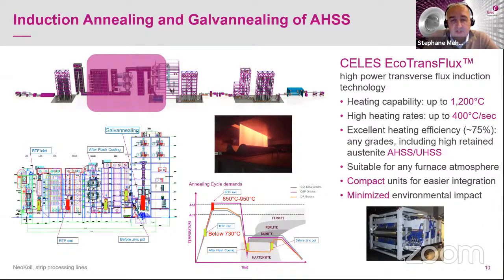About 15 years ago it developed this technology for stainless steel lines, because basically this technology can heat any kind of material, magnetic or non-magnetic, and can get to very high temperatures. As you can see, the limit is far above what is required today, 1200. Heating rate is very important as well. And with this, we can efficiently heat at high heating efficiency any grade, including high retained austenite Gen 3 advanced high strength steels. Another type of application for this transverse flux is for galvannealing.